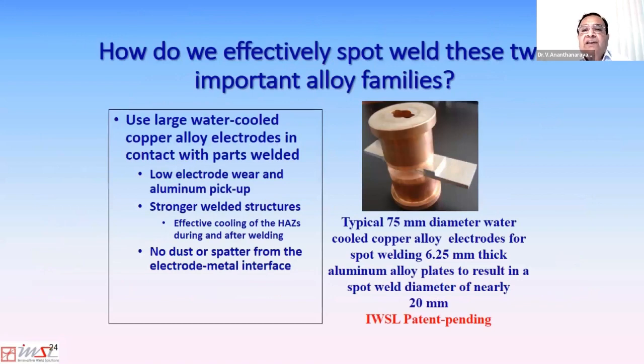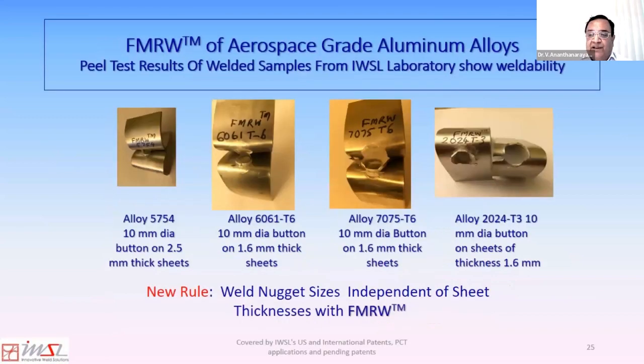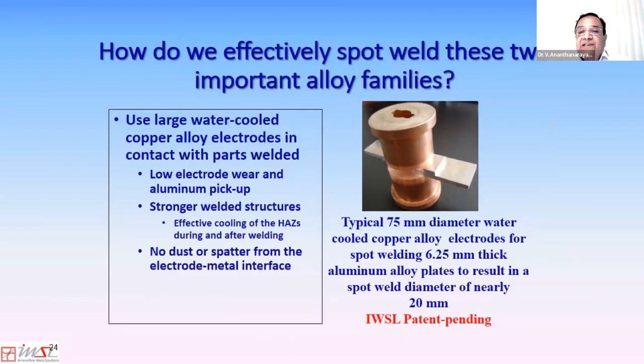For instance, here we are resistance spot welding 2 aluminum alloy plates. Each plate is 6.25 millimeters thick. And normally one would not even attempt to resistance spot weld these plates. And if you see the copper alloy electrodes I'm talking about, you see how large they are and how they cool the heat affected zone during welding.